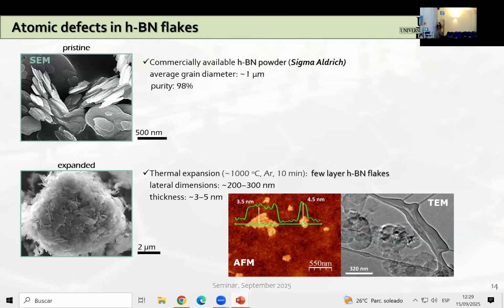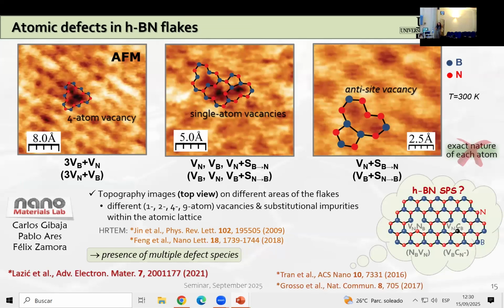Now, the atomic force microscopy characterization of hBN flakes also shows that we have a presence of different vacancies, like 4-atom, single-atom, or anti-site vacancies within our flakes. There are also other defects such as 2 or 9-atom vacancies or some other substitutional impurities, but those that I show here are the most frequently appearing in our flakes. Of course, the anti-site vacancy can be, for example, nitrogen or carbon related, in which case there is a nitrogen atom missing and the nearest boron site is substituted by either a nitrogen or a carbon atom.